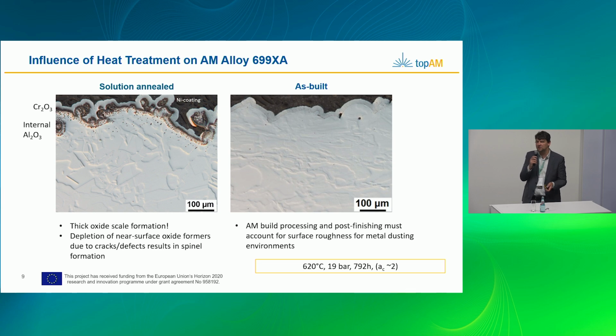So obviously what we need for this type of corrosion is a surface treatment, and also the alloys themselves need a heat treatment usually after the building process when you want to use them for high temperatures. So they need to be solution annealed, because you have a lot of aluminum in there. You have other elements that during the AM process basically form precipitates that are unwanted. So we need to solution those and then reprecipitate them for the highest strengths.